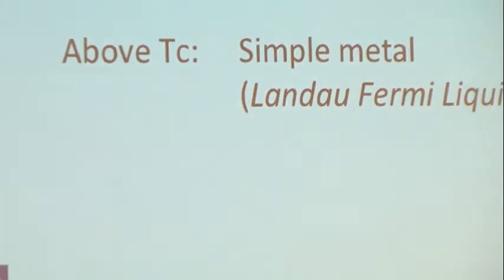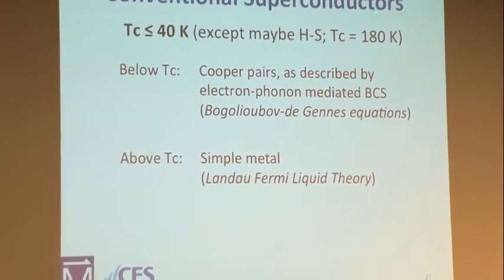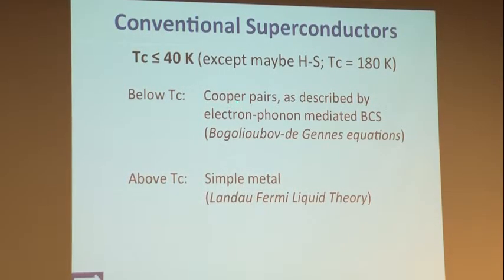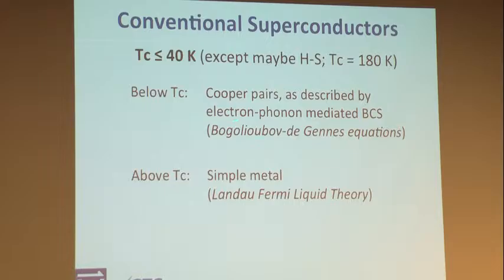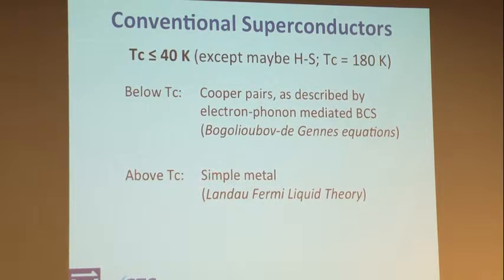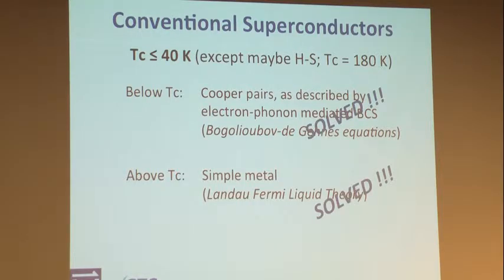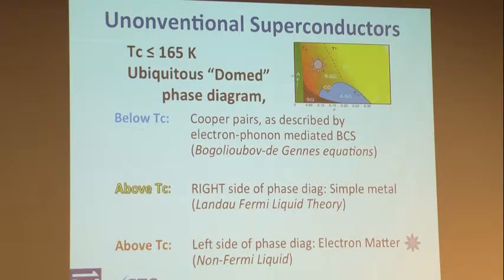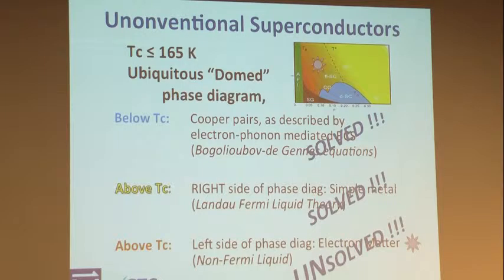Conventional superconductors, TC is typically below about 40K, except for this new one I don't want to talk about because I don't understand it, but it's incredibly cool. Anyhow, below TC, Cooper pairs, as described by electron-phonon-mediated BCS and Bogoliubov-de Gennes equations, work just fine. Above TC, we can describe everything as a Fermi liquid. Solved. Unconventional superconductors: TCs are typically under 165 degrees, and they have this ubiquitous domed phase diagram. Below TC, Bogoliubov and de Gennes still help us out. Above TC, on the right side, it's Landau-Fermi liquids. Above TC on the left side, it's a non-Fermi liquid, not even a near Fermi liquid. And that is what is unsolved in physics.